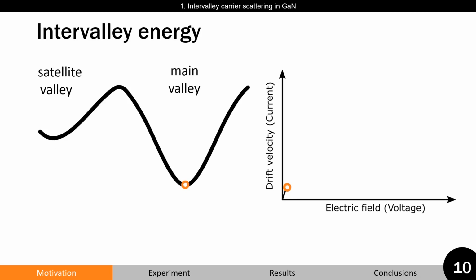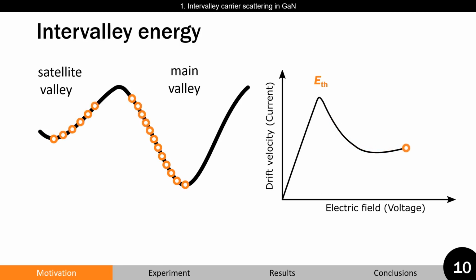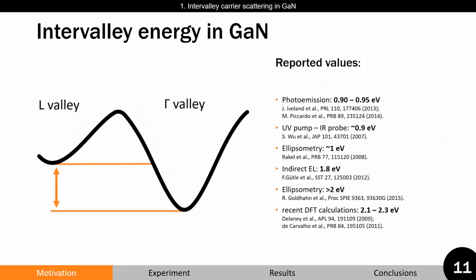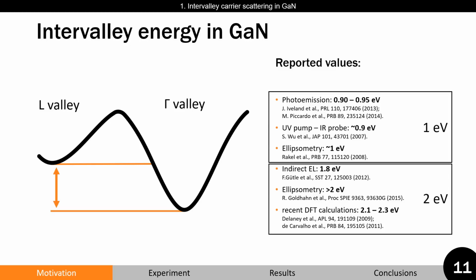By applying an electrical field, we start to populate electrons on the main conduction band. After the threshold energy is reached, intervalley carrier scattering can be induced. The satellite valley has lower mobility, therefore, with increased electrical field, overall electron velocity is reduced. In the case of gallium nitride, this value is still disputed. Reported values could be grouped into two groups, around 1 electron volt and 2 electron volts.